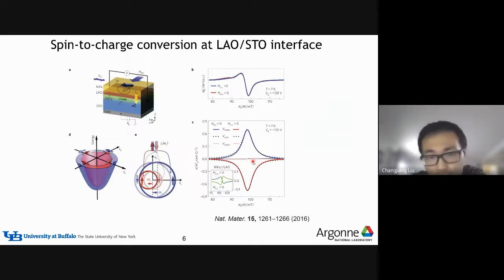So another thing is this system can show very high spin orbit coupling. Basically, it can be used in spintronics research. People found that the electron gas flowing in this interface can show a very large spin Hall angle, and they used ferromagnetic resonance to basically excite a spin current, and that spin current can be injected into this interface.